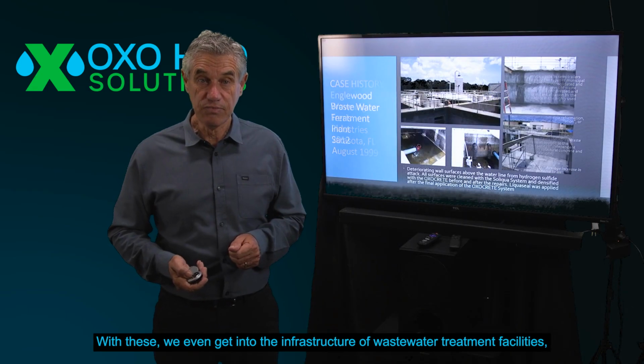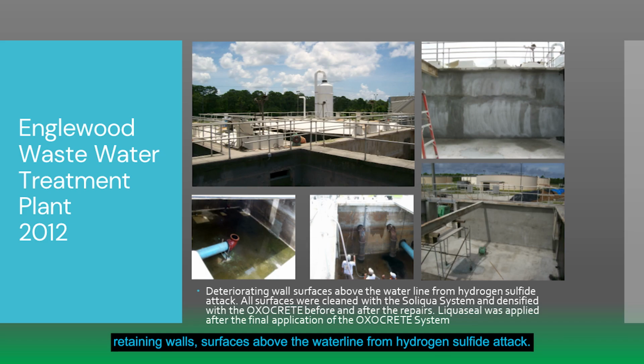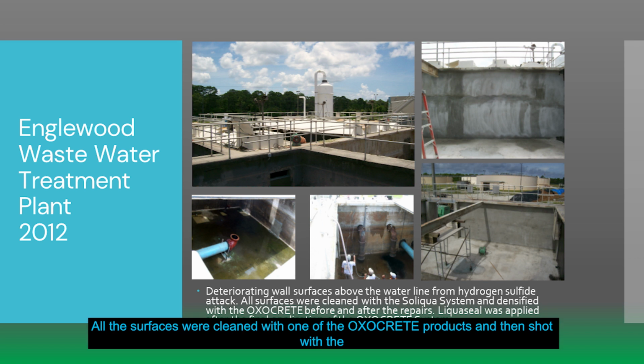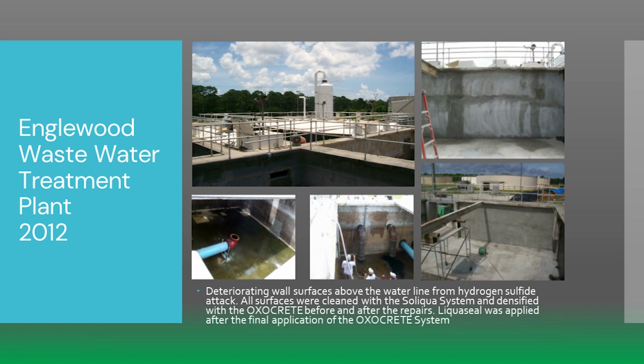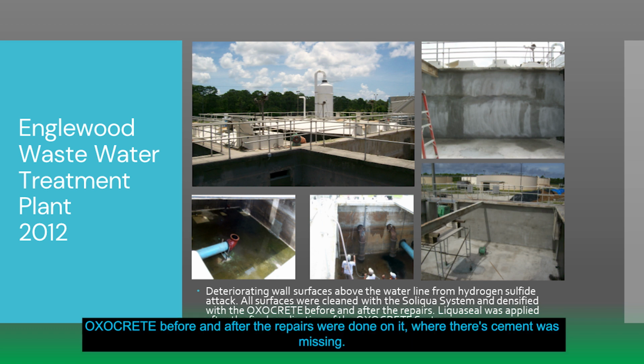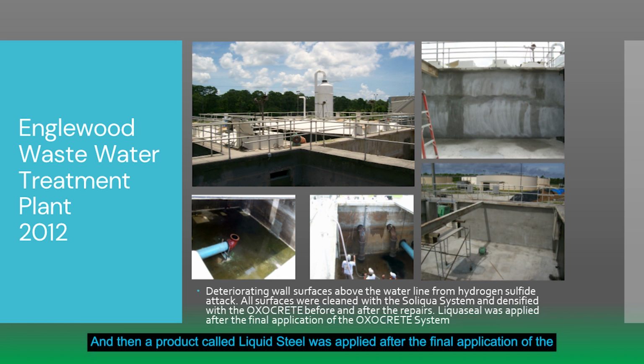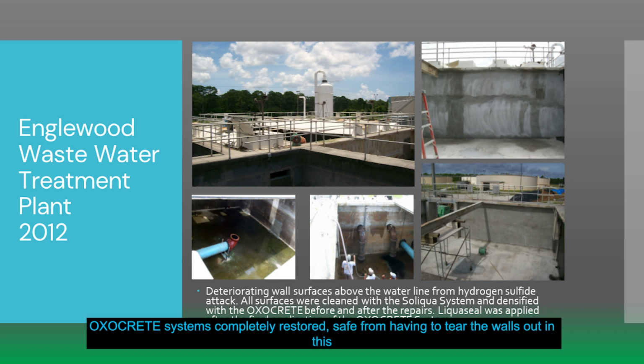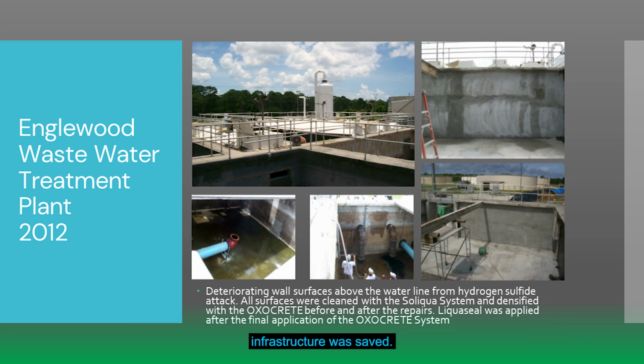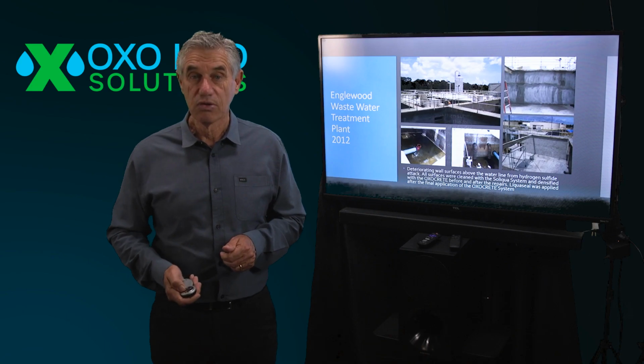On and on and on with these. We even get into the infrastructure of wastewater treatment facilities. We treated retaining walls and surfaces above the water line from hydrogen sulfide attack. All the surfaces were cleaned with one of the OXOCRETE products, and then shot with the OXOCRETE before and after the repairs were done where the cement was missing. And then a product called Liquaseal was applied after the final application of the OXOCRETE systems. Completely restored, saved from having to tear the walls out, and this infrastructure was saved.